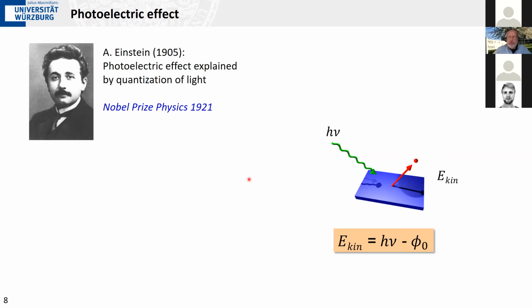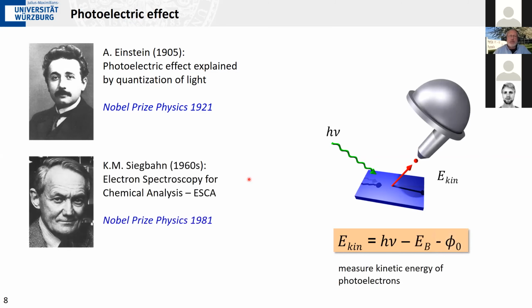And the first one who really turned this into a useful tool was Kai Siegbahn in the 1960s, where he utilized or turned this into a spectroscopy by detecting or measuring the photoelectron energy distribution. And by assuming that you have energy conservation in this photoexcitation process, you can then get information about the original binding energies of the electrons in the solid.